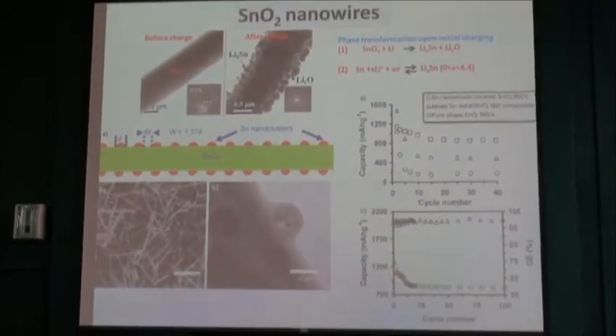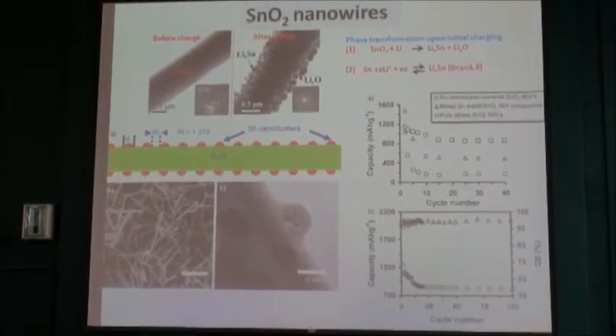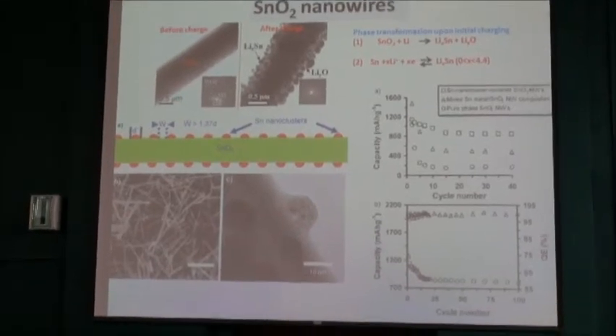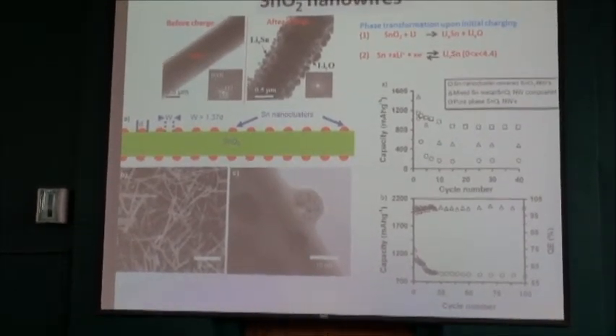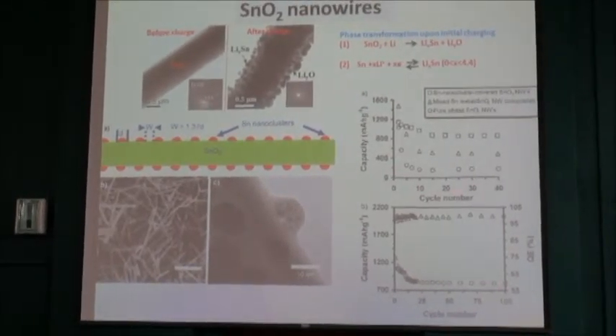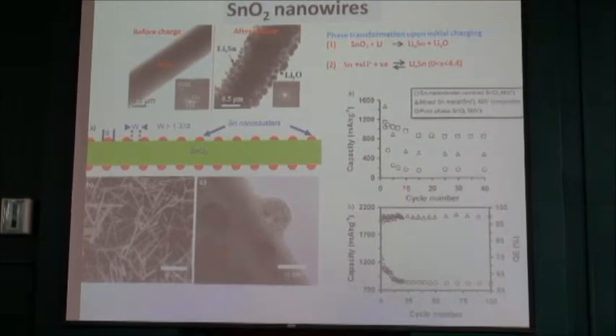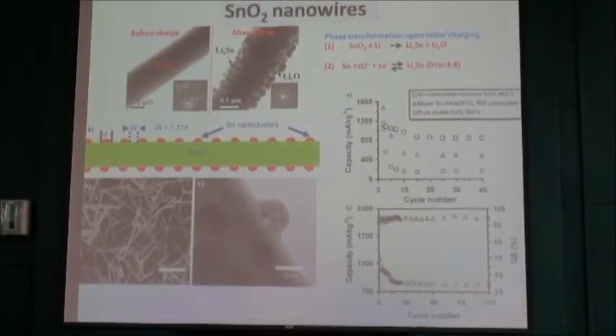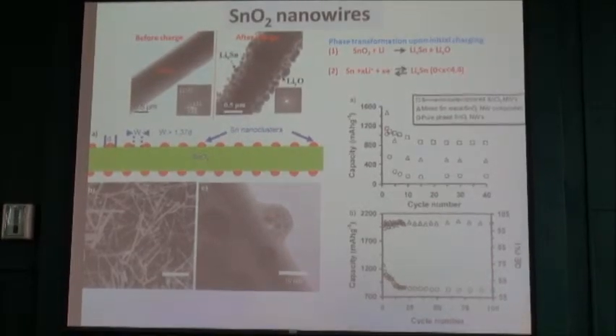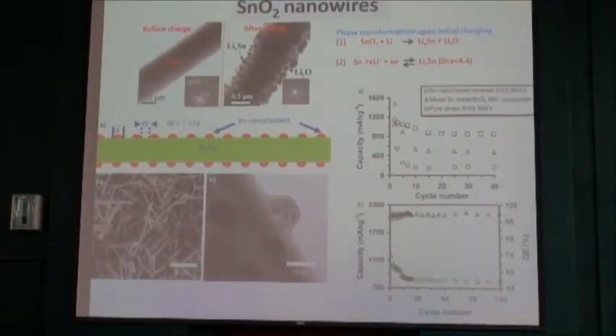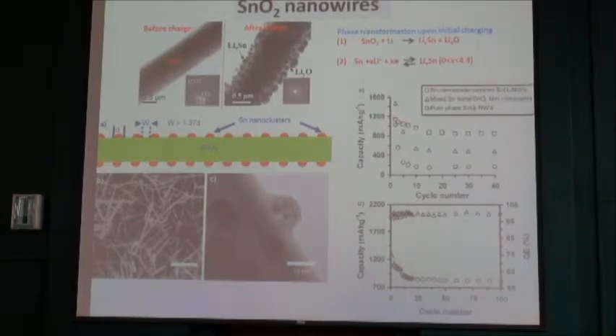So when we did this, here are the TEM images. This is the nanowire and this is how the clusters are deposited. This curve shows you how that works. This is the capacity, this is the number of cycles. If I use just nanowires, the first curve with the circles, without these metal clusters, you can see initially we have very high capacity, like 1600. After the first cycle, it goes down to almost 400 and eventually becomes very small. That means your structure is going to disintegrate. So it's not good, right?